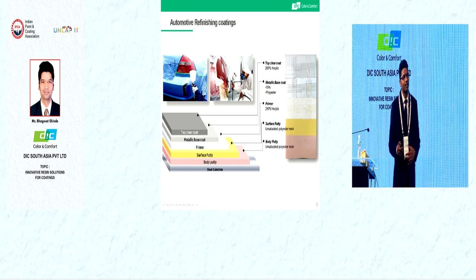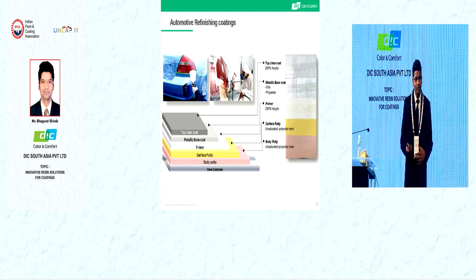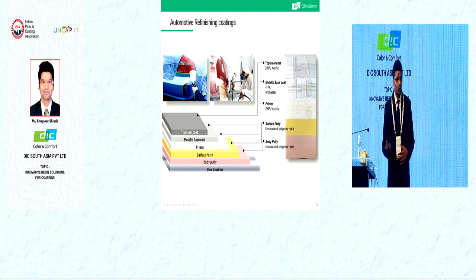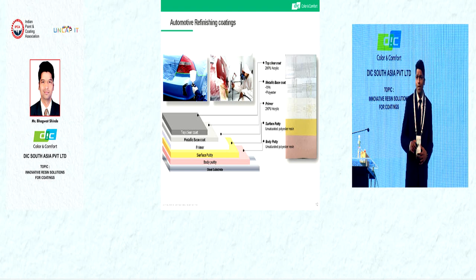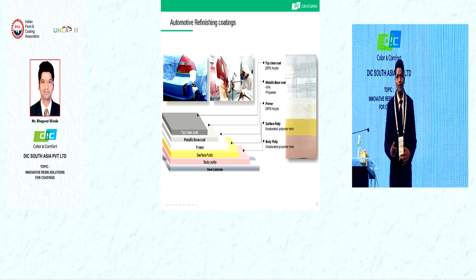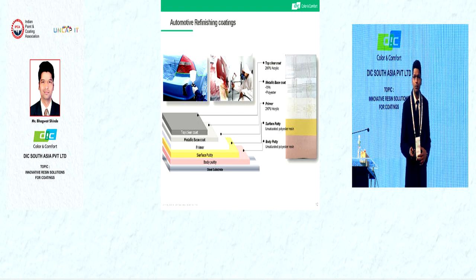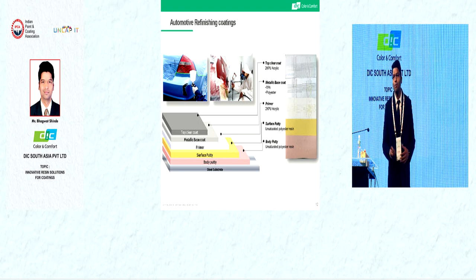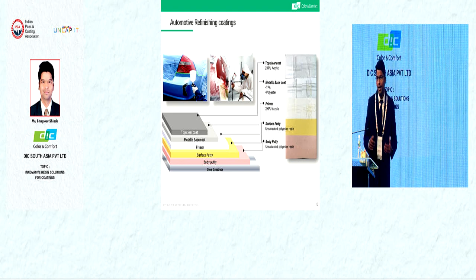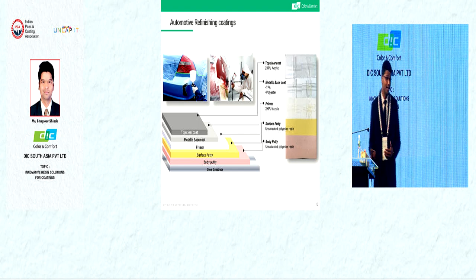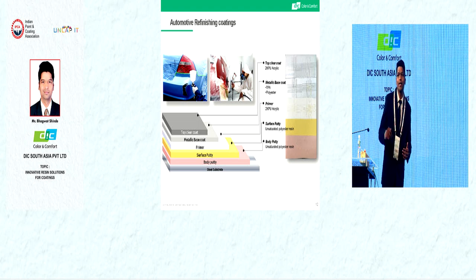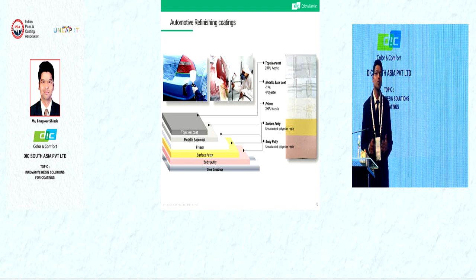After the putty application, we have to apply the primer, and the primer is generally a 2K acrylic product. The primer should give good adhesion to the putty as well as fast drying and good sandability properties. After the primer, we apply the base coat and then the clear coat. Base coat is generally 1K acrylic, 2K acrylic, then 1K polyester or TPA resins. In the clear coat, we generally apply 2K PU products. The end properties of the coating layer depend upon the acrylic products in the clear coats, mainly on the hydroxy values.